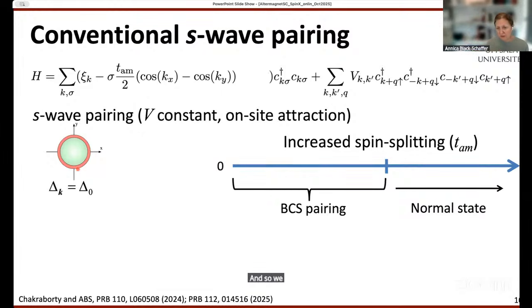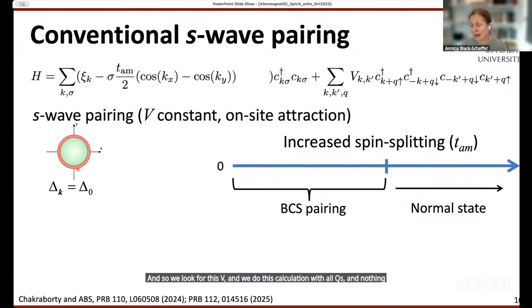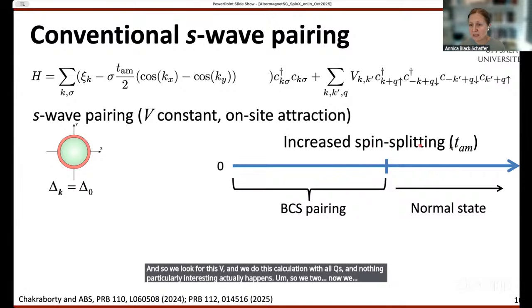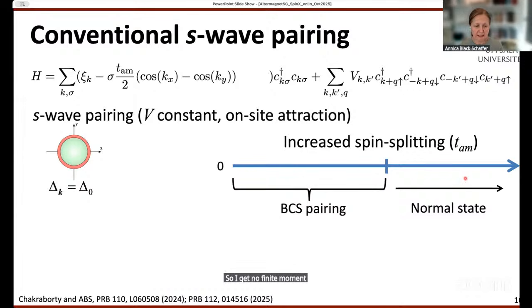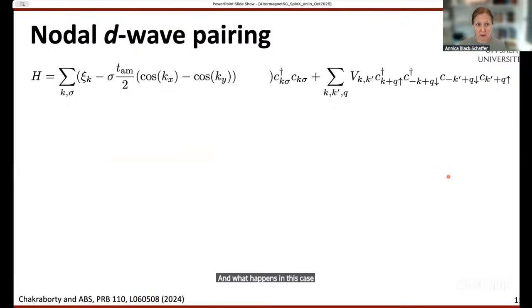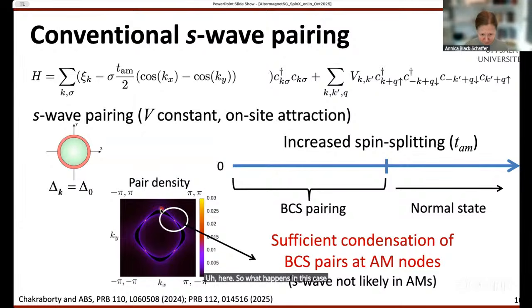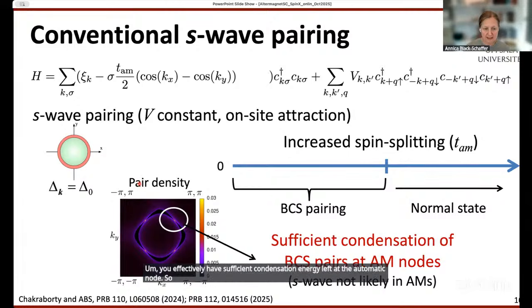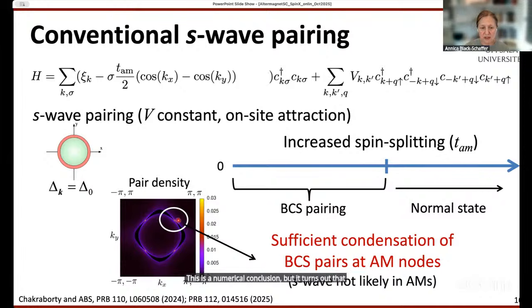And so we do this calculation with all Qs, and nothing particularly interesting actually happens. We tune the spin splitting TAM, and we start from a BCS pairing, and it lasts for quite some time. At some point it breaks down and I get the normal state. So I get no finite momentum pairing in this case. What happens here is that you effectively have sufficient condensation energy left at the altermagnet node. Here I plot the pair density in the Brillouin zone, and you see it's really peaked at this point here, which is the altermagnet nodes. It's a numerical conclusion, but the condensation energy I get by pairing at these nodes is enough to get BCS pairing, and you never go into finite momentum pairing.